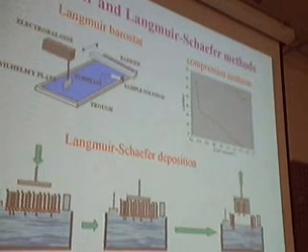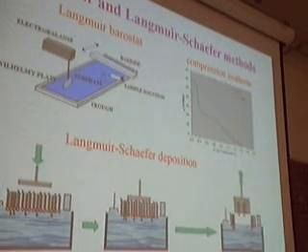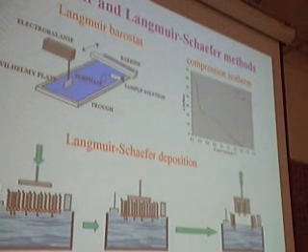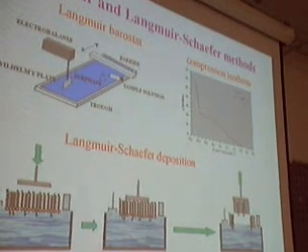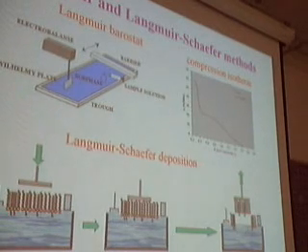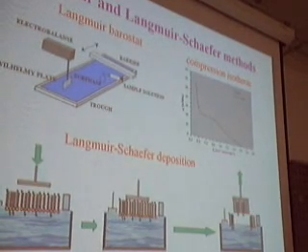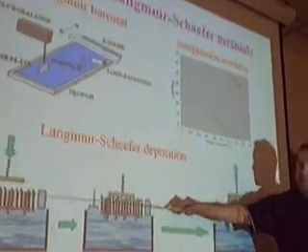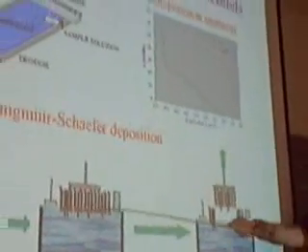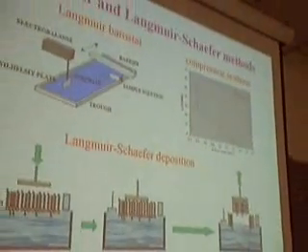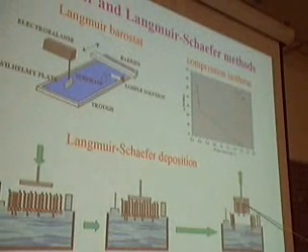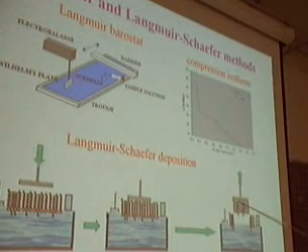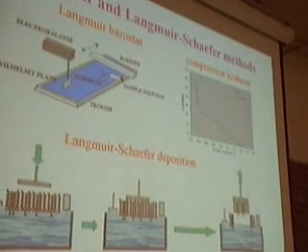Then we may proceed with processing these films, and as I said, it's also possible to transfer this film from the air-liquid interface to a solid substrate, and this can be, for example, simply done by this kind of technique. We have a solid substrate that is simply brought into contact with this film, we let it react, and then lift up, and then eventually we have a film adsorbed, attached to this substrate. I'll come back to how this interaction can actually be controlled.